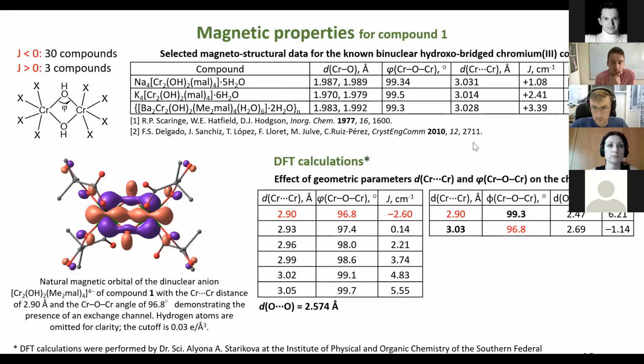In order to determine which of these parameters exerts a stronger effect on the character of the exchange interaction in complex 1, we performed additional DFT calculations, including variation in metal-metal distance, which led to a change in the chromium-oxygen-chromium angle at a constant value of chromium-oxygen distance. As can be seen from the table, weak antiferromagnetic exchange, due to the presence of an exchange channel, was predicted in the case of a chromium distance of 2.9 angstroms and an angle of 96.8 degrees.